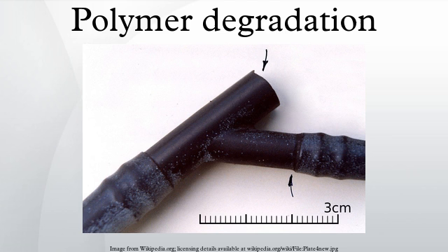Polyethylene, polypropylene, and polymethyl methacrylate are sensitive to oxidation and UV radiation, while PVC may discolor at high temperatures due to loss of hydrogen chloride gas, and become very brittle. PET is sensitive to hydrolysis and attack by strong acids, while polycarbonate depolymerizes rapidly when exposed to strong alkalis.